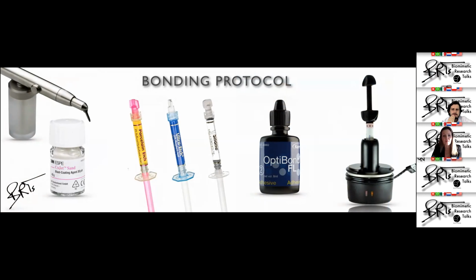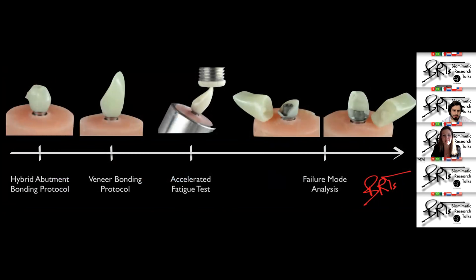Just to clarify, as a time frame to understand what was done, we bonded the mesostructure into the T-base that we fabricated manually. And then we bonded the veneer on top of this composite resin metal abutment, the hybrid abutment. We waited 24 hours and then loaded in the accelerated fatigue test, from 40 newtons to 280 newtons, or until it fractured. And once the fracture occurred, we analyzed under the microscope the failure mode of those restorations. That was what was done.